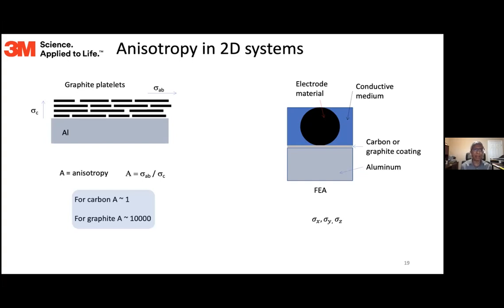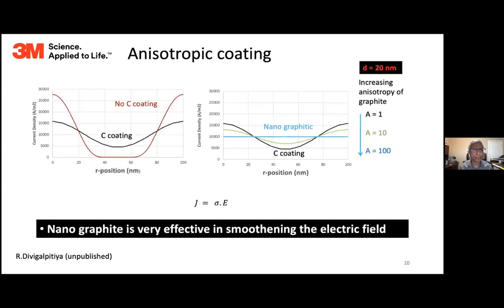Whereas in graphite or in graphene, the ratio can be as high as 10 to the 5. So more than 10,000 for sure. Now you can use that property and do the model again. Just a very simple model: a spherical particle contacting through an interface, an aluminum or a metal piece. We do the proper calculation, putting the right numbers through this one. This is what we find.